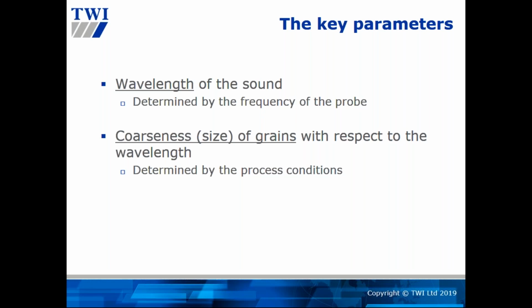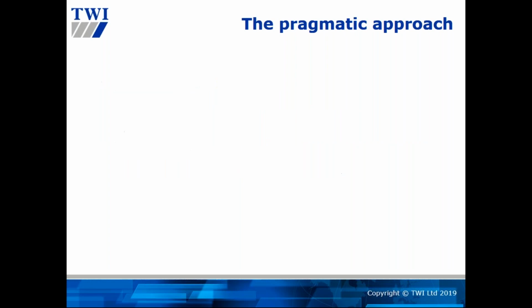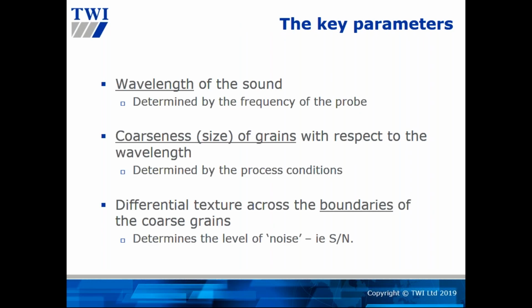And certainly laser cladding will have its own morphology and microstructural characteristics. And then the texture that develops across the boundaries of these grains has a big influence on the level of signal to noise. And signal to noise is an important parameter for determining the quality of a technique, because ultimately it also has a bearing on what kind of flaw, or how small a flaw, you could be sensitive to.